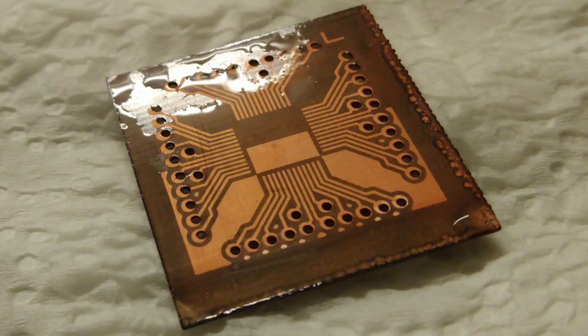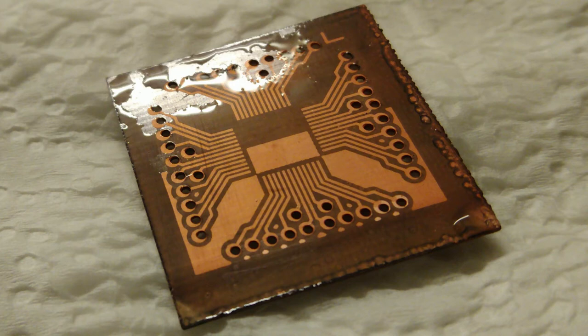If you look closely, the photoresist patterns are a negative image. That is, the photoresist is present where we do not want copper. I tried before using a positive image and just dipping the PCB in a copper etchant, but this approach didn't work, as it's hard to protect the copper inside the holes from the etchant.